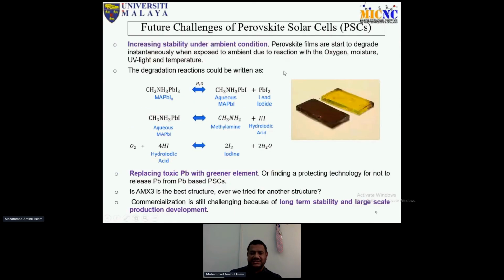So what are the challenges now? The first challenge is stability under ambient conditions. Perovskite films start to degrade instantaneously when exposed to ambient air due to reaction with oxygen, moisture, UV light, and temperature. So here is a simplified equation of how it degrades. This is methylammonium lead iodide, which is the perovskite material. When it touches oxygen or humidity, it absorbs this humidity, absorbs the water molecule, and then it decomposes. You see lead iodide and then aqueous methylammonium iodide. And this one again decomposes to methylamine and hydrogen iodide.